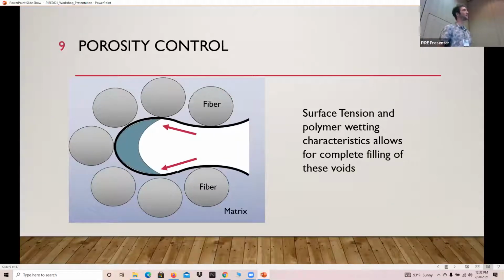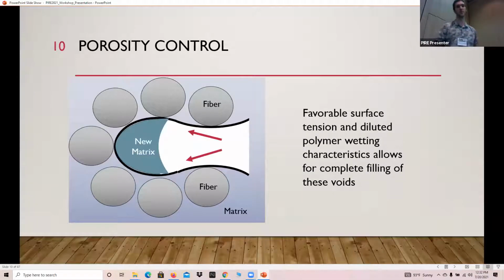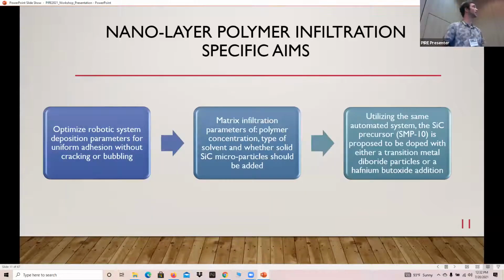It's blocking it. The favorable surface tension and polymer wetting characteristics of a highly diluted SMP10 allow it to actually fill this back void first. You actually get it pulling off of here because of the convexity and concavity of the surfaces here. It'll actually pull that polymer back into the back and fill in the whole void as we move forward, and thus allowing new matrix to fill in everything.